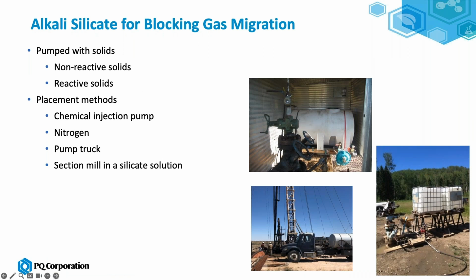A few different options, and these are from different field trials in Canada and the US. A lot of times silicate is pumped as is. So to the top right, that's a 3.2 ratio sodium silicate, diluted 1:1, being pumped in for a vent flow in northern Alberta. To the right, that's a sodium silicate. In this case, a setting agent was combined with the sodium silicate to get the desired set time, and that would be the 4.5 ratio, so the low sodium product.